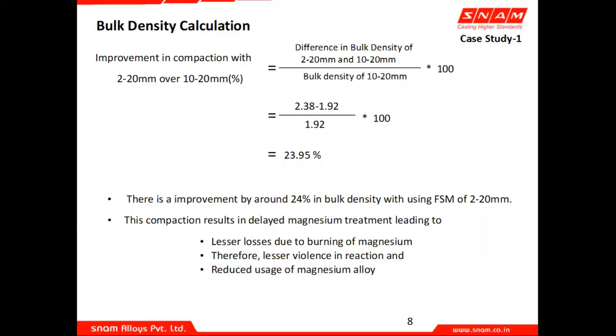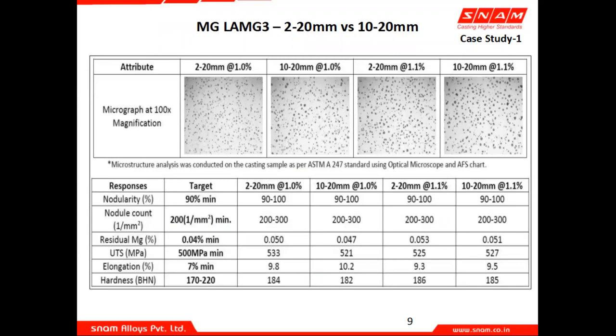So as I told you, because of this, there are going to be lesser losses due to burning of magnesium, because the metal cannot immediately react over the whole surface area of a larger material and create the violence and the volatility and the burning losses. So what can happen with this is you can work on a reduced usage of magnesium alloys also. So how do we go about it is what we did, the experiment at the R&D center.